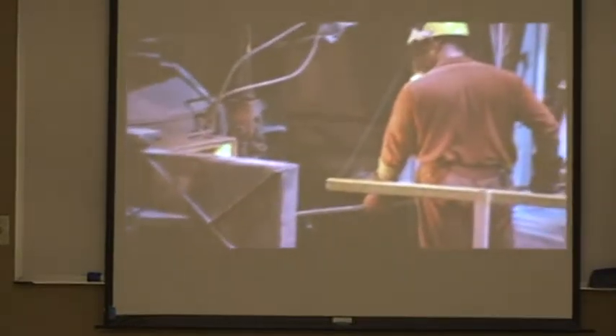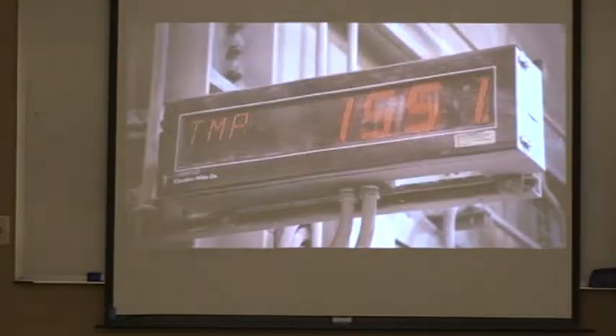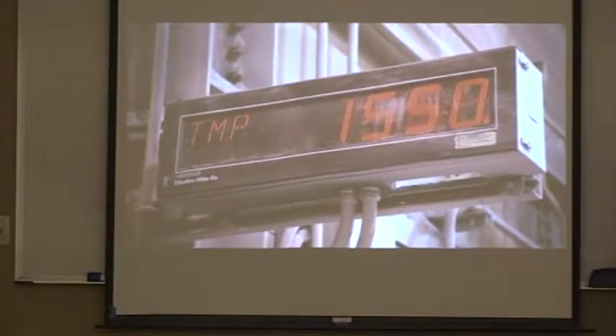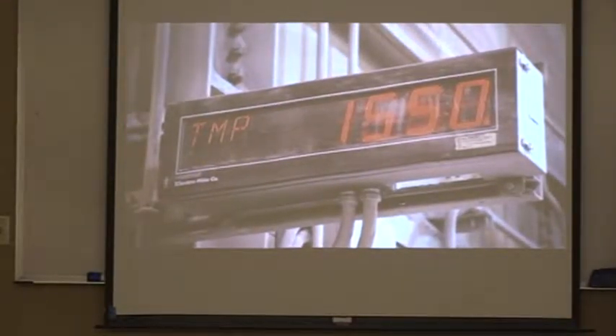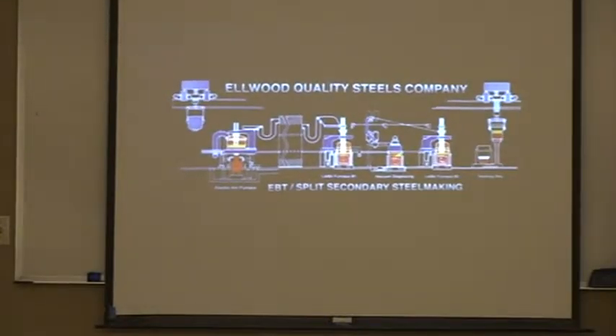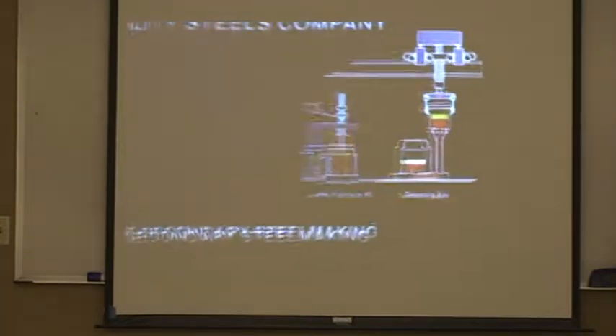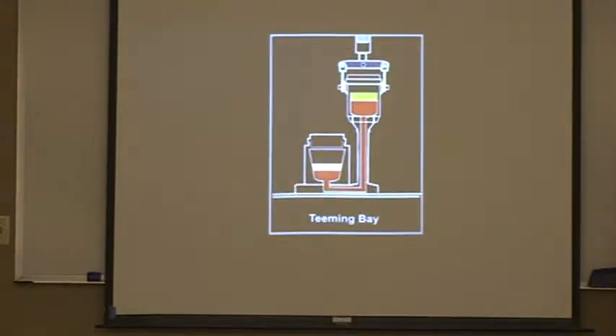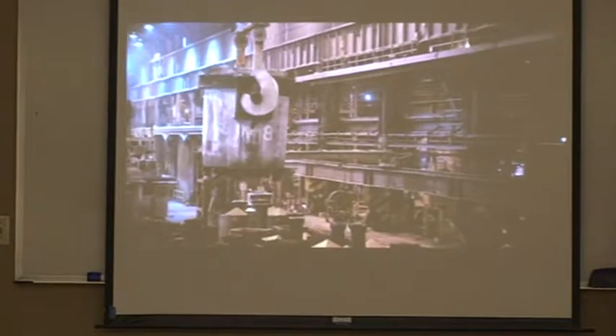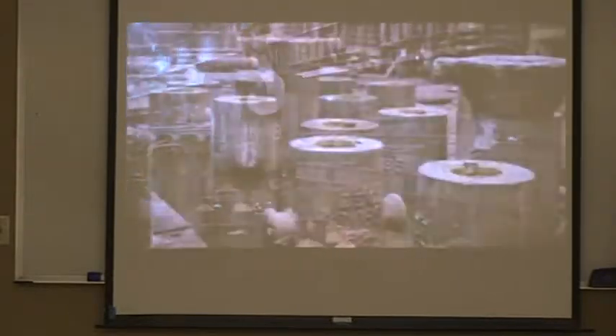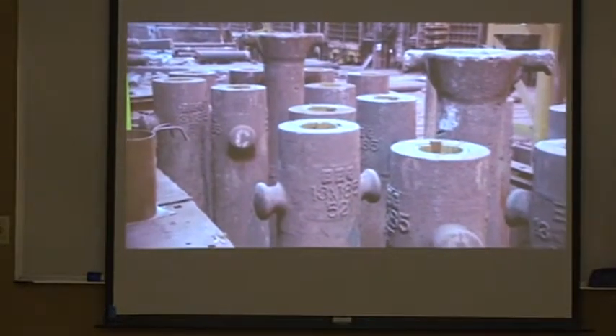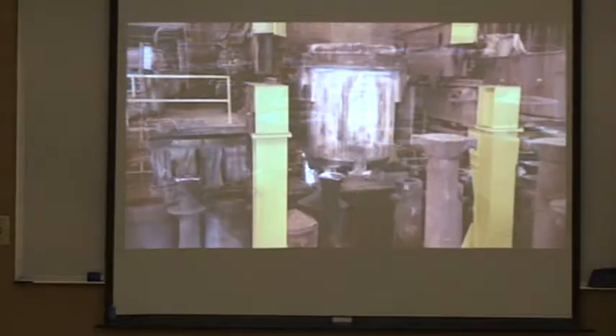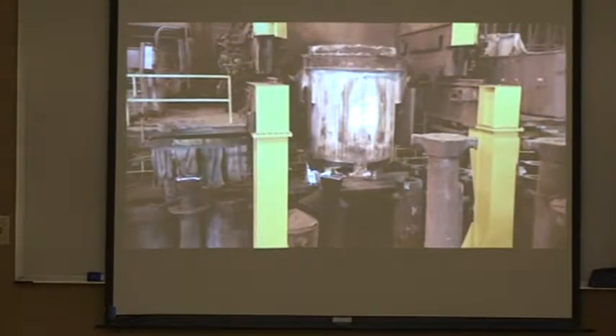The teeming temperature is controlled to within 5 degrees Celsius. A precisely controlled teeming temperature is critical for producing high-quality forging ingots. In the teeming bay, dry, clean molds are set up for each specific heat. The ladle is centered over the trumpet, and the slide gate is open.